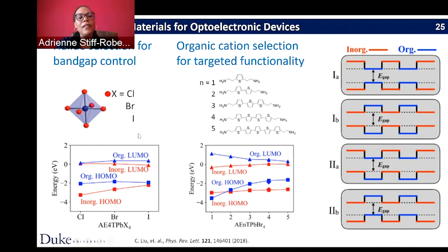And what's interesting here is that as you change what the metal halide is, you change the band structure. And as you change the number of thiophene rings in this material, you change the band structure. But what's really interesting is what you see here, where when you look at the relative positions of the band structure for the organic part and the band structure for the inorganic part, there's a crossover here, which basically means that by controlling the halide that you choose and controlling the size of the organic molecule, you can get different types of self-assembly of quantum wells for that energy band lineup.